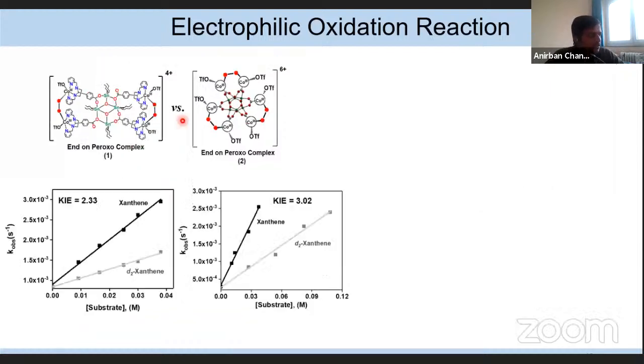To get further insight, I determined the KIE value using xanthene and d2 xanthene, and the KIE value is around 2.3 for the peroxo species 1 and 3.02 for the peroxo species 2. The positive KIE value confirms that the CH bond abstraction takes place at the rate determining step of this reaction.